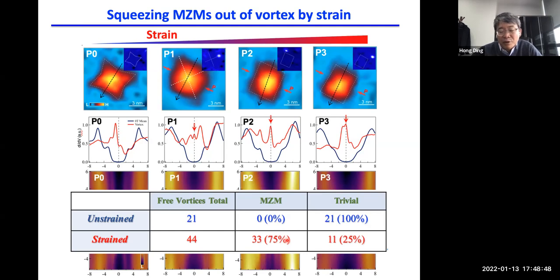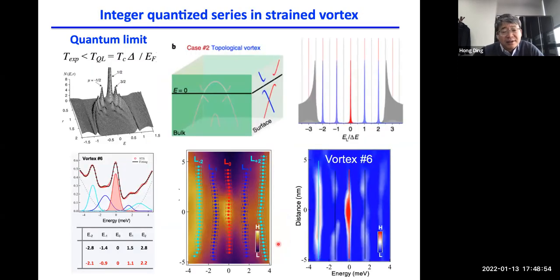And if we apply more strain, we will achieve 100% for all the vortices having the zero mode. This is also discrete, clearly shown here with zero, plus or minus one, plus or minus two.